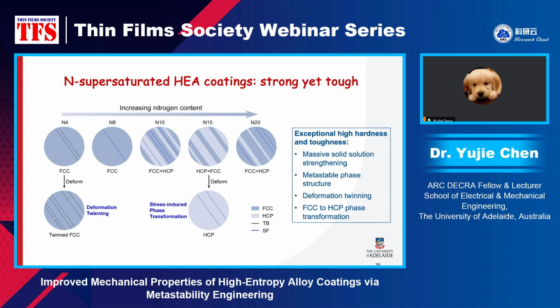So therefore, they show high hardness and also high toughness. As we increase the nitrogen content, there may exist a sweet point at which we achieve the best synergy of hardness and toughness. And it may not be this one, the N15. We think it will be more efficient if we can use theoretical calculation to get the design of this metastable high-entropy alloy coating. So if anyone is working on the theoretical calculations or simulations, we are happy to collaborate.